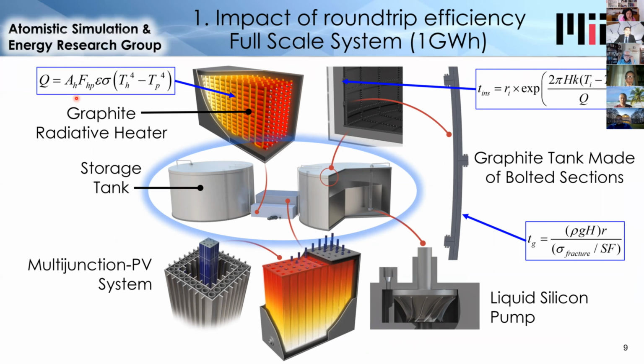And so if we start at the top left going clockwise, we look at the graphite heater. These U-shaped heating elements can be made from graphite or tungsten, and electricity is passed through them just as with a commercial oven, like a residential oven, and it generates heat, which is radiated out at pipes containing silicon. So there's heat transfer between the electrically heated resistors and the silicon. And the key equation that was used to develop this heater was the radiative transfer between the two, because this determines how hot the heater gets.